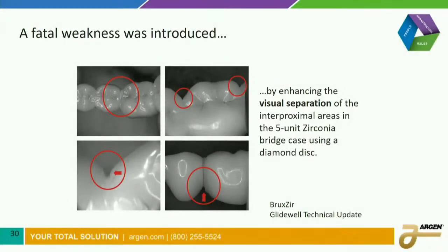Now, we get units back, and this one happens to come from Glidewell because I like the way they illustrated it. You see, when you use a diamond disc on a sintered zirconia, you can't get away with it if you send it in for analysis. You can't say, oh, the zirconia broke, because the diamond disc leaves a fingerprint, and I could find that fingerprint. And we've gotten so good at it now, I could even tell if the diamond disc has been worn, and say you need a new diamond disc. But you shouldn't use a diamond disc on sintered zirconia at all. I know you want to get the visual separation between them. Try and do that in the milled state